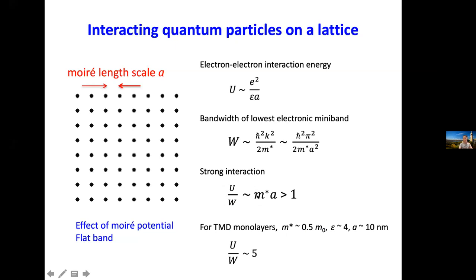This ratio is proportional to the mass of the particle and also the spacing. So without considering the moire potential, for TMD materials, the mass is on the order of half an electron mass, and the dielectric constant is about 4. For a typical moire period of 10 nanometers, you get this ratio already around 5. And if you consider the strong moire potential, this ratio becomes much bigger.